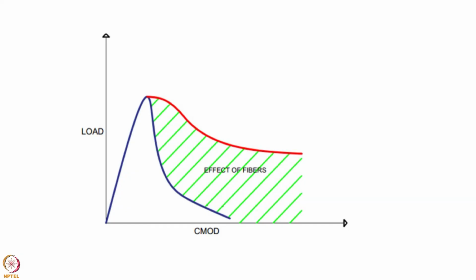Now this is a typical load crack opening response of plain concrete and fiber reinforced concrete. As you can see, in the case of plain concrete, there is a sudden drop after the peak, which shows a brittle failure. Whereas in the case of fiber reinforced concrete, there is an enhanced post-peak load carrying capacity, which is due to the stress transfer by the fibers across the crack, which was captured in the test that we've shown now. So this characterization of fiber reinforced concrete was done using the closed loop testing system with displacement control. And thank you for watching.